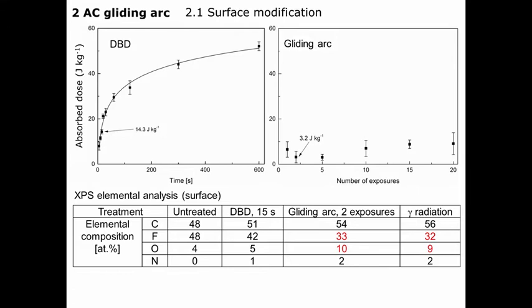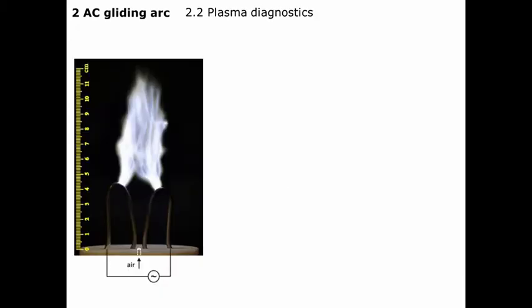You can see the red one. Gliding arc can affect the surface chemistry very much, reducing fluorine and increasing oxygen compared to DBD. So in these particular cases, gliding arc can be surface modification dominated, but DBD in this particular case can treat both of them. That's a kind of surprising result, which I wanted to share.